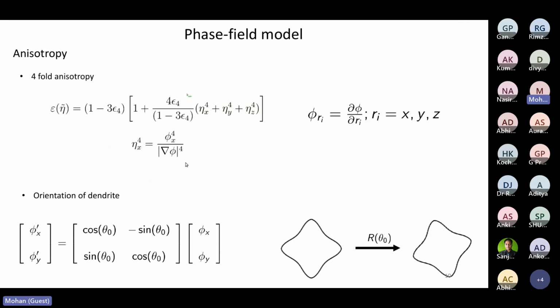One more thing I would like to mention here is, when you do dendritic solidification, in the solidification pattern we tend to see a fourfold or sixfold kind of symmetry, which comes from the anisotropy of the interface energy, which is normally expressed in the form of these functions of the normal vectors to the interface. And if you want to rotate a dendrite, you can apply a rotation matrix. For example, it is in 2D. In 3D, you have a 3D rotation matrix. So these expressions are simply given.